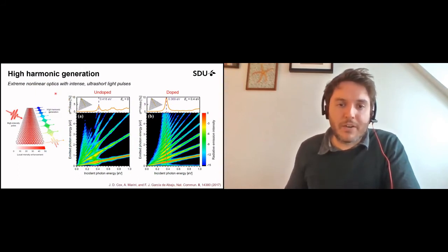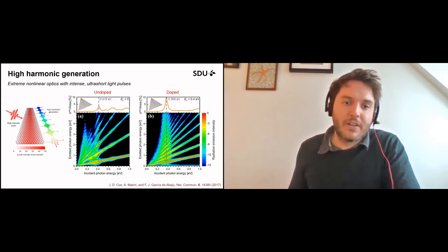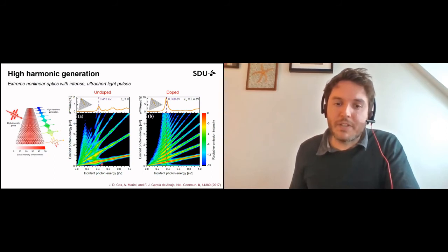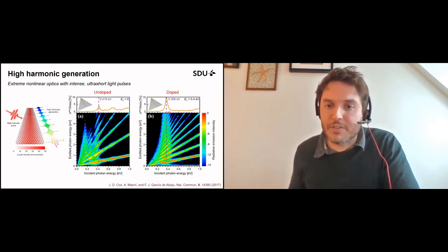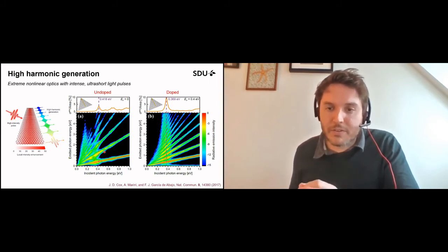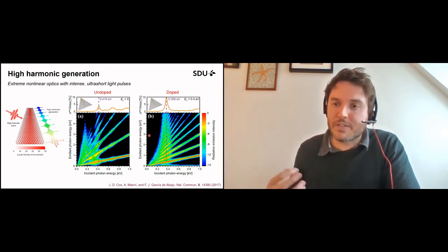I've also been looking at how you can go for extreme nonlinear optical phenomena when you illuminate with really intense electromagnetic fields. You resonantly excite the plasmon and you can generate high order harmonics of the plasmon that you've resonantly excited. And this, of course, occurs more efficiently when you resonantly excite the plasmon. You can see harmonics, not only second and third order harmonics. Here we're going for second, third, fourth, fifth, up to 13th or something. So this is also a way you can generate intense ultrashort light pulses.